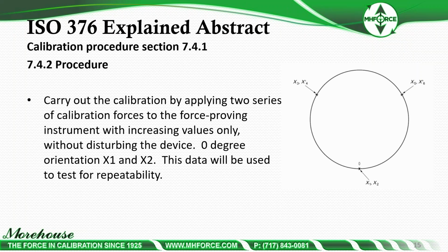The procedure in 7.4.2 is to carry out the calibration by applying 2 series of calibration forces to the force proving instrument with increasing values only, without disturbing the device. 0 degree orientation, X1 and X2. That's down here. That data is going to be used to test repeatability only. So we're going to take the instrument, we've already exercised it, and then we're going to put it in the 0 position. And then we're going to do our 8 to 12 forces. Remember, we recommend 12, ISO only requires 8. And then we're going to do them a second time without disturbing the instrument. And that's going to give us our X1 and X2 value.